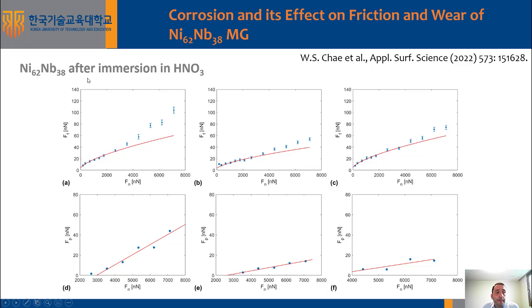Now, importantly, after different durations of immersion into nitric acid, we find that the shear strength does not really change. However, the amount of plowing force, meaning the amount of abrasive wear or of plowing friction, significantly decreases. So that means by growing a niobium oxide on the surface of this metallic glass, we are essentially retarding abrasive wear, and so extending the regime of shearing friction.